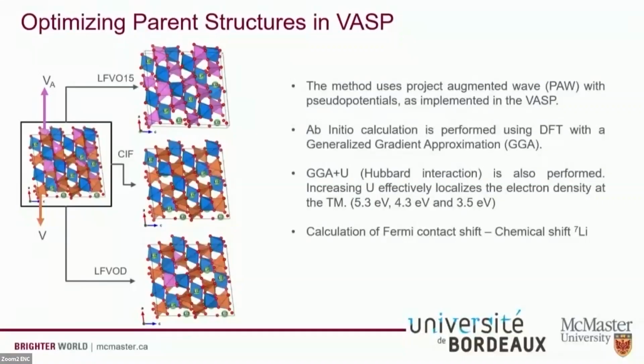What we did was 3 different calculations using the PAW method and applying generalized gradient approximation, so GGA, and also using the Hubbard interaction, or the +U term. This term in particular localizes the electron density at the transition metal centers and gives us a closer approximation of the experimentally observed shifts. And we use this method to calculate all of the lithium shifts in the structure in 3 different structural configurations. So we did energy optimizations of the original structure, the new structure that Tiana determined with fully the pink polyhedra, and then a mix, because we know that about 15%, or 1 asymmetric unit of our full unit cell, is populated by this new orientation of the vanadium centers.